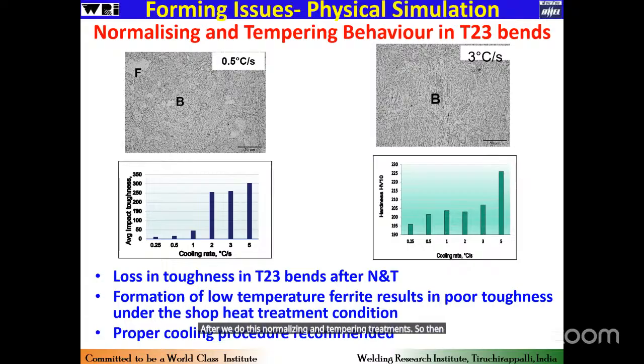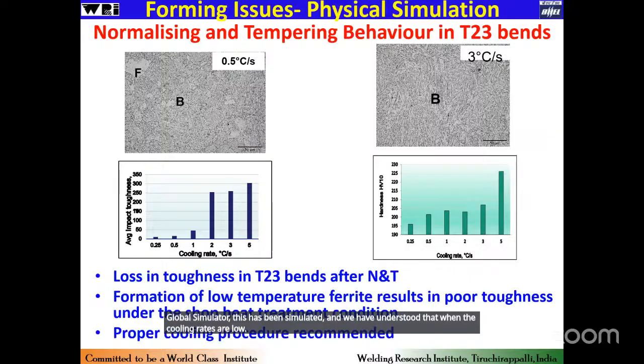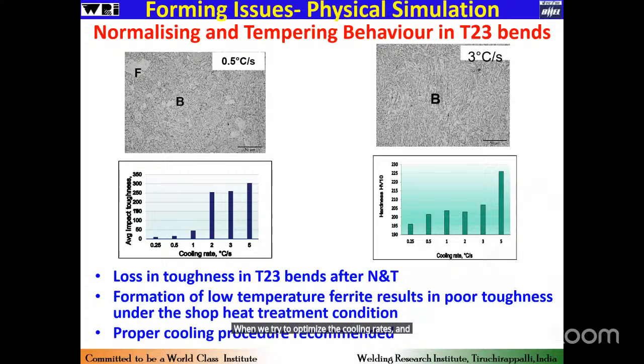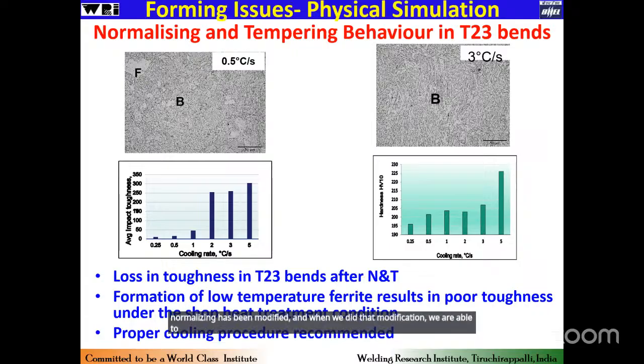So then, as I said earlier, with the facility of WRI of thermophysical simulation called the Gleeble Simulator, this has been simulated. And we have understood that when the cooling rates are low, some deleterious phases, especially the ferrite-based deleterious phases, are forming, and that is actually the culprit for the reduction in toughness. So when we try to optimize the cooling rates, and when the cooling rate crosses the critical value of 2 to 3 degrees per second, then we are able to achieve the required toughness, especially the impact property. So based on that, the cooling after normalizing has been modified. And when we did that modification, we were able to achieve the required toughness properties.